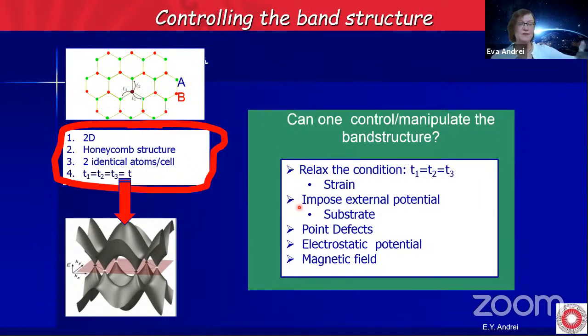So you can have a superstructure that flattens the bands. You can pluck out the individual atoms, and that gives you point defects, which have very interesting magnetic properties. You can apply an electrostatic potential, and that changes the Fermi energy. You apply a magnetic field, and then you create flat bands. So these are a lot of strategies that you can use to change the band structure of this two-dimensional material.